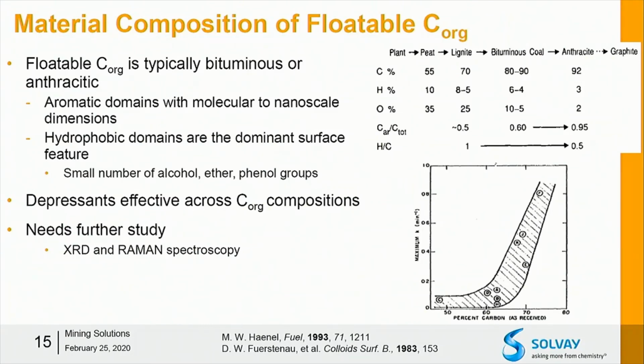Okay, and the thing that's probably least understood about carbon is actually its material composition and how it impacts flotation. So it's known that carbon can be very variable, and sort of the real correlation that's most useful is to think about it like coal, even though it is quite different. But as you have increasing sort of atomic carbon in the composition, it goes from lignitic, bituminous to anthracitic carbon. Becomes more hydrophobic, you have fewer and fewer oxygen groups, more and more aromaticity, and it tends to float better. You don't really see carbon floating if it doesn't at least sort of in the lignitic or bituminous